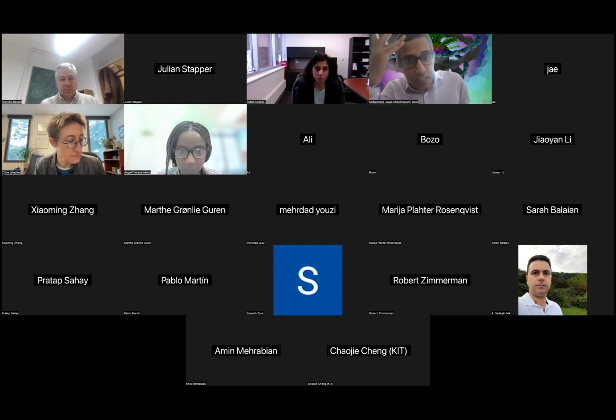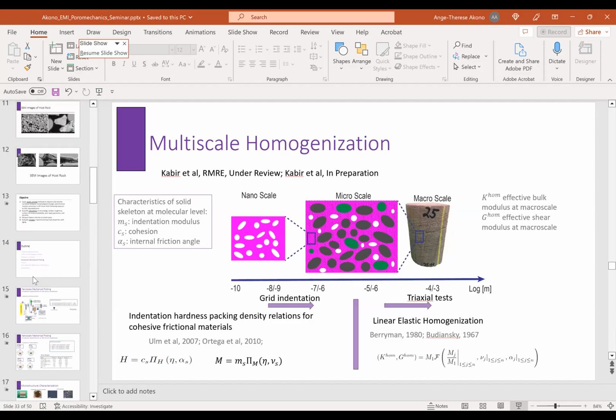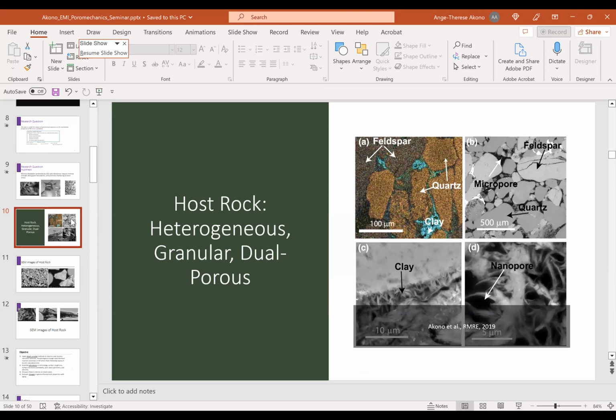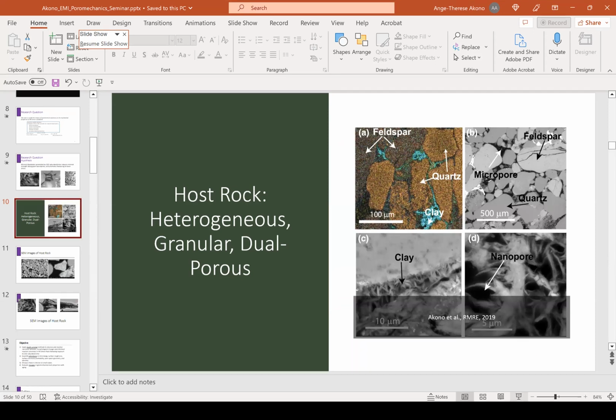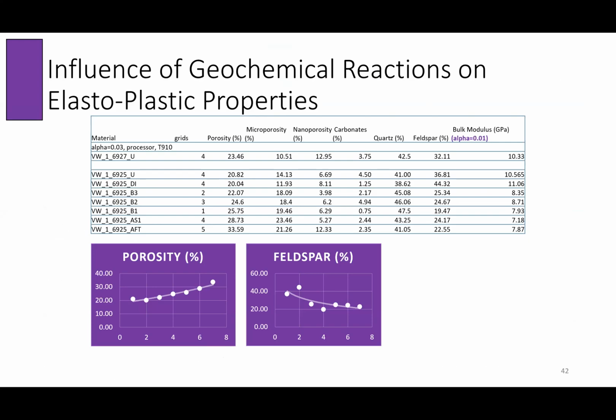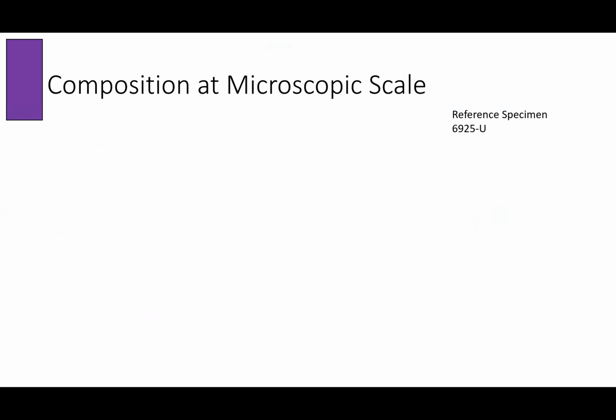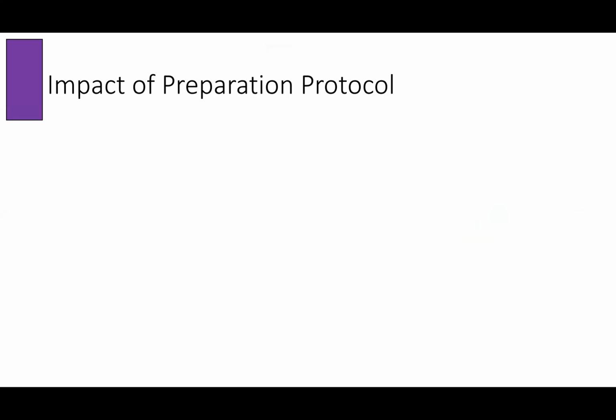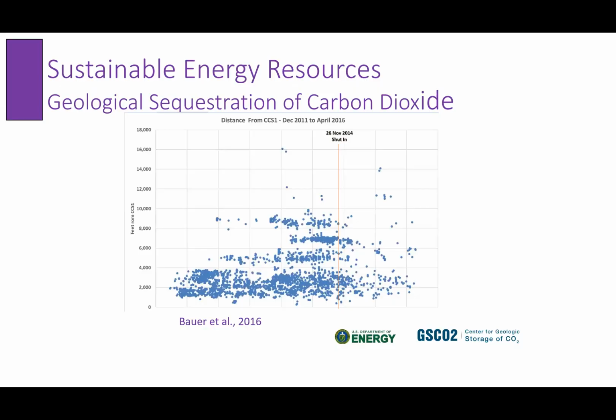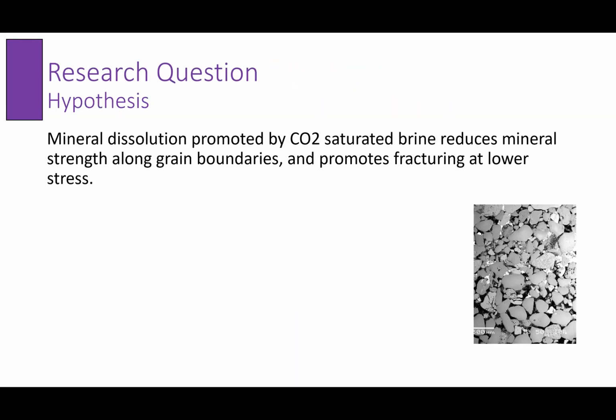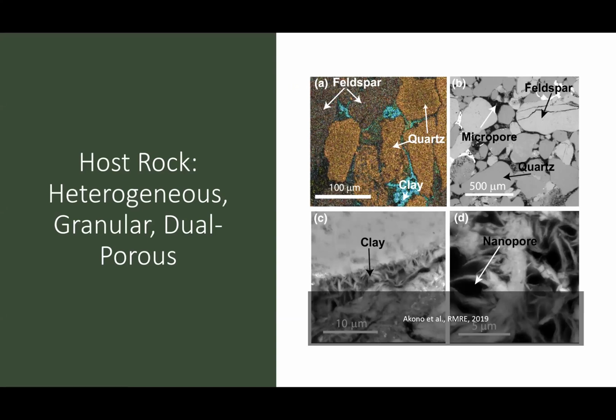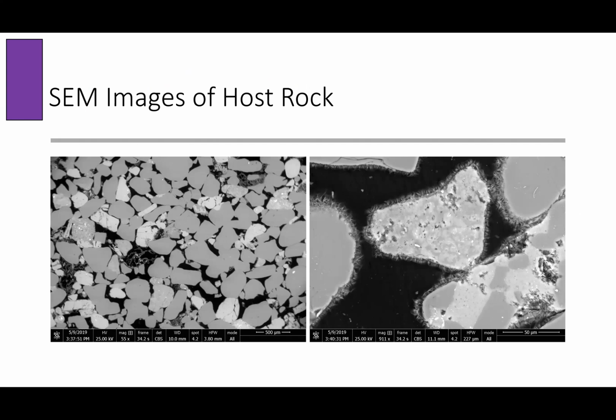Yes. So we have a lot of feldspar in our samples. Let me go back. Let me show the feldspars first, these aluminosilicates, potassium aluminosilicates and sodium aluminosilicates. So carbonates like calcite, other phases? For this sample we didn't have calcite. Okay. It was very quartz rich, and what was very interesting to me is that I saw that you have some sort of a mildly acidic solution, and then the quartz is dissolving. Yeah. So it's kind of counterintuitive because quartz dissolves at relatively higher pH.